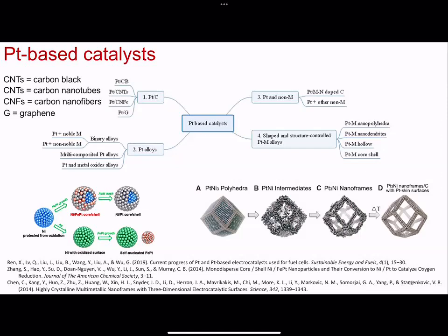like 1950s materials science here. The diffusion rates of these atoms make them mobile. So if you have something like platinum and nickel, you could start off with something that looks like this. Here's the 111 surface, here's the 100 surface. Then if you wait over time, the diffusion rates of these two species form these cages, and in the end you have structures that look like this. I think if you wait like 2 weeks, you go from the polyhedra to this empty cage.